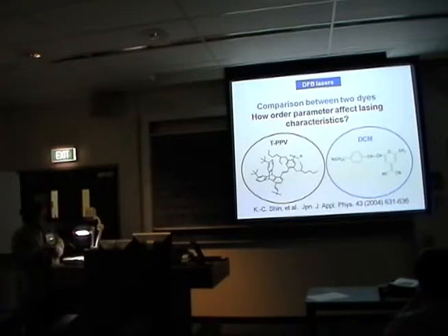So for that purpose, I will introduce the comparison of the DFB lasers using this dye and this dye. This is a commercially available dye molecule, and this is a gift from Tim Swager at MIT. This dye has the advantage that the dipole moment along this direction is well aligned to the liquid crystal director because of this triptycene group, the liquid crystal molecule.